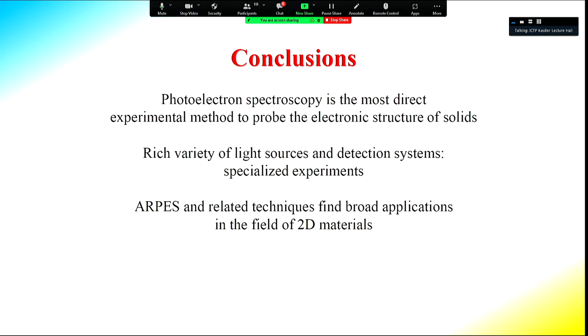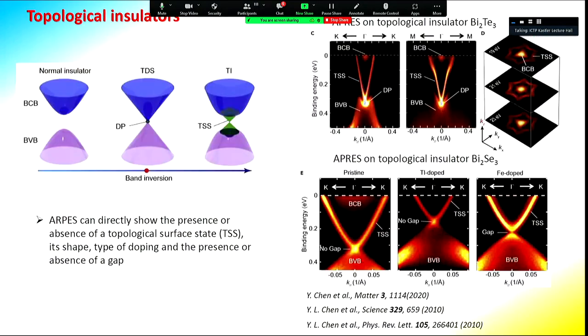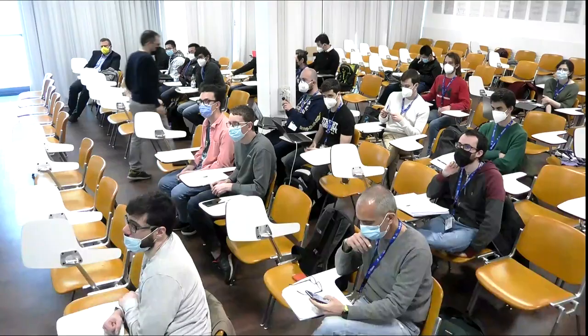So thank you very much, Polina. I think there were very nice examples from which to start the discussion. Let me start with a comment on the example of silicene on silver. One of the points of this talk is that ARPES is a very powerful technique to get the band structure and to directly connect with what we do. But there are a lot of technicalities, which Polina was discussing: the photon energy, the sensitivity to the surface, the substrate, etc. So we have to pay attention, when we do a calculation, not to jump to the conclusion that we can directly describe what is measured experimentally.